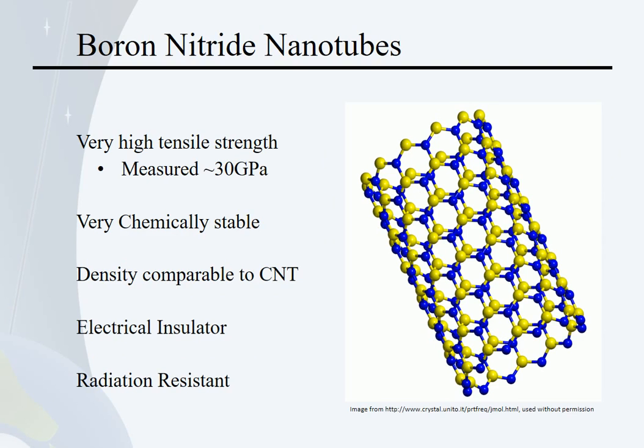The other one to talk about is boron nitride, which we just mentioned. They have a very similar structure to carbon nanotubes, where you've got these six-membered rings, cages of them wrapped into tubes. In this case, though, we have two atoms alternating, boron and nitrogen. They average out to the same mass as carbon, and the bond length is similar. So boron nitride has roughly the same density as carbon nanotubes.